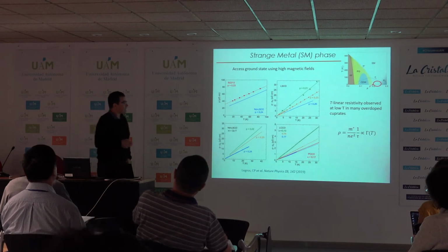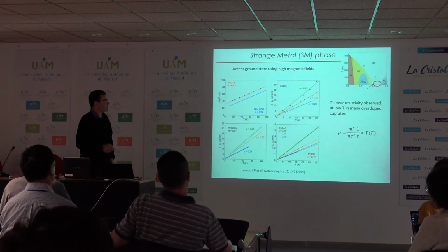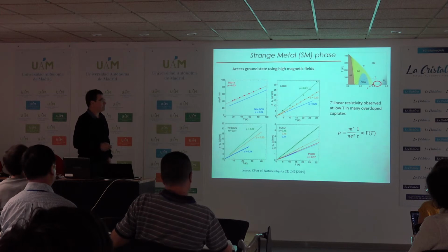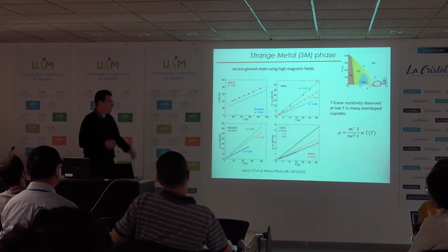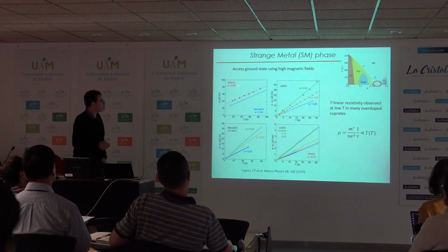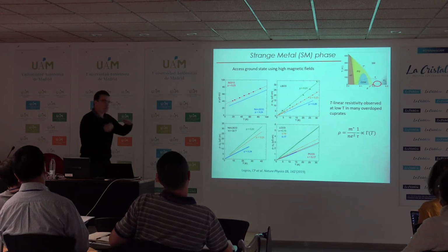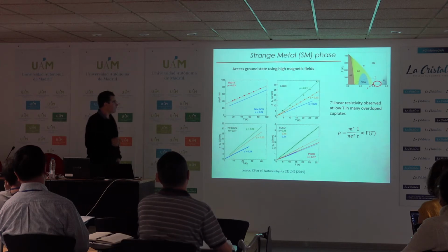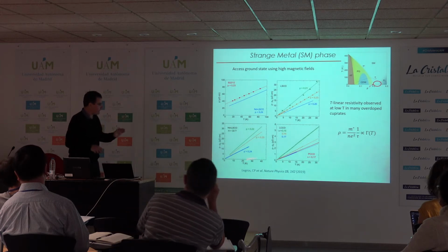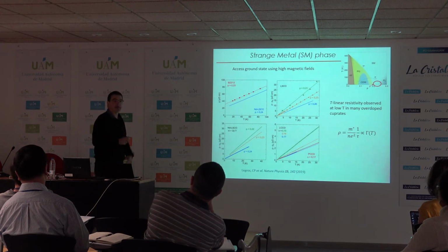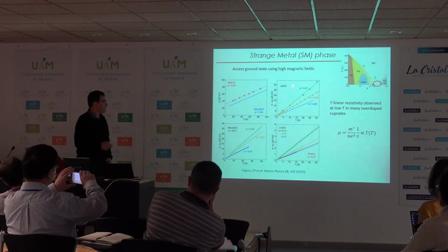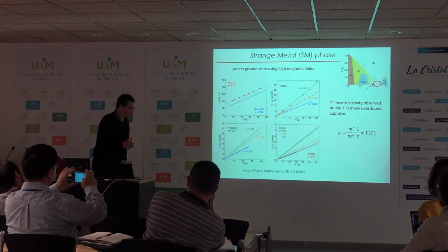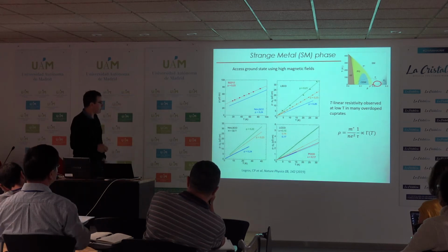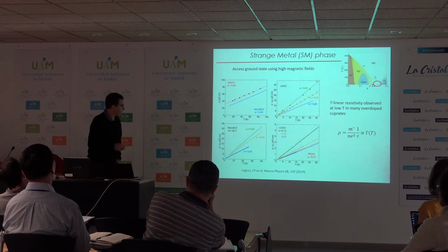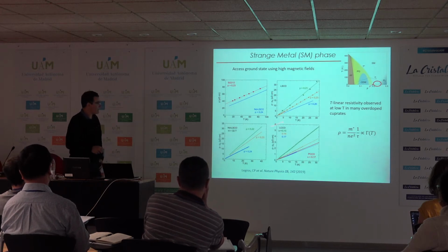So we have recently done some measurements in this strange metal phase, but now at low temperature by applying a magnetic field to quench superconductivity. We have done this in the two-layer BISCO 2212 compound, and we have also compiled in this paper some results obtained in different families of cuprates. Namely LSCO, so this is work done in collaboration with Nigel Hussey 10 years ago. In Nd-LSCO, this is the transport measurement done by the group of Louis Taillefer, and in some electron-doped cuprates, LCCO and PCCO.